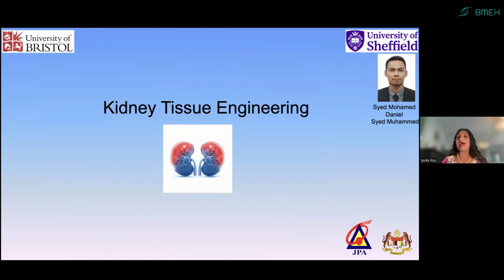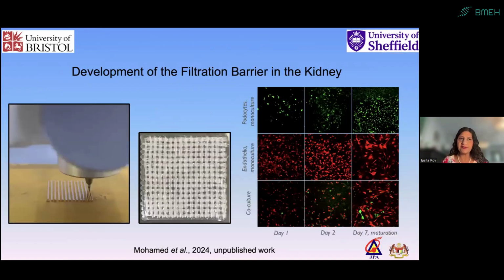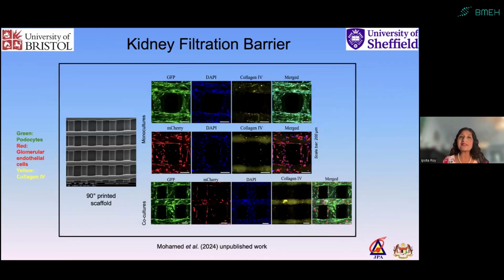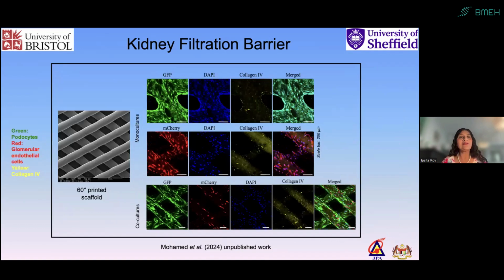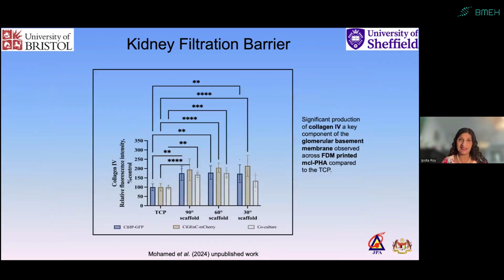I only have 2 minutes left, so I'll quickly pass through what else I have done, a few of the things like kidney tissue engineering. We're looking to create a filtration barrier within the kidney, and here we have the polymer over which we have grown these kidney cells, the podocytes, the endothelial cells, co-cultured them, and we have observed excellent growth of these cells on our 3D printed structures. So here you have a 90 degrees strut, we have 60 degrees angled strut and 30 degrees, and in all of them we saw very nice collagen formation and cell growth.